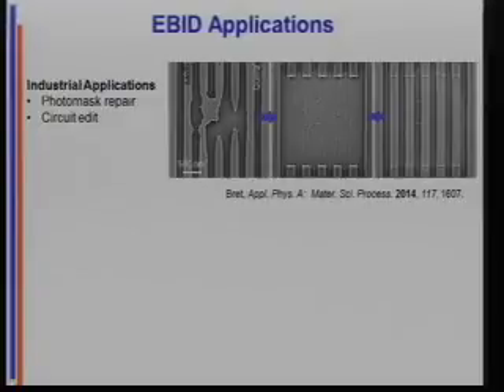And so they repair these. They come in with an ion beam, cut out the area that is defective, and that's this. This is with the ion beam cut. And then you take EBID, electron beam deposition, and you write the lines back in. Okay. And then you can also do what's called circuit edit. This is for prototyping integrated circuits, where you design a circuit, you make it, and then you discover that this really ought to connect to that after the fact, so you can draw the lines back in.